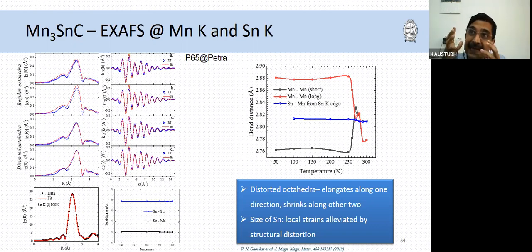So it is the strain that is created by the different A-type atom, say gallium or tin, because their sizes are different, that makes the octahedra distort differently. That gives these different properties to these antiperovskites, very simple looking antiperovskites, but it is essentially the distortion of the manganese octahedra that gives you these properties.